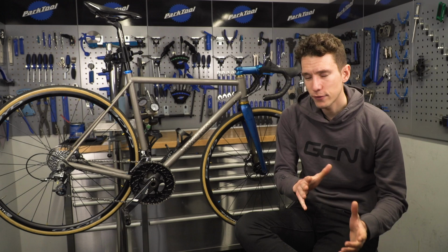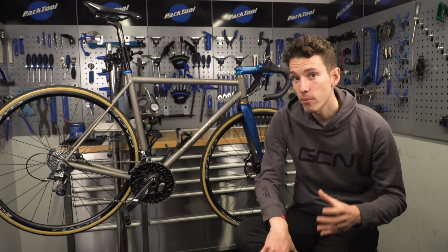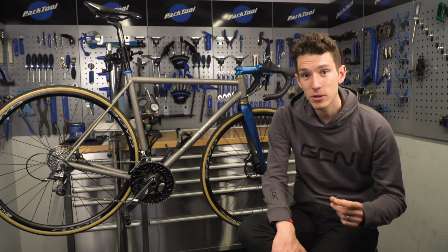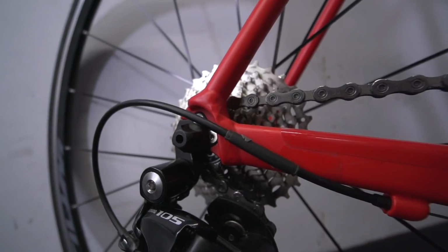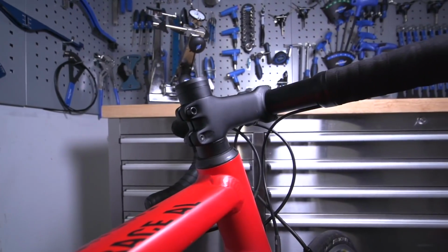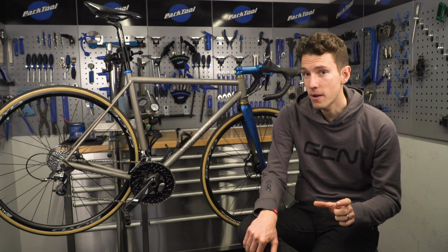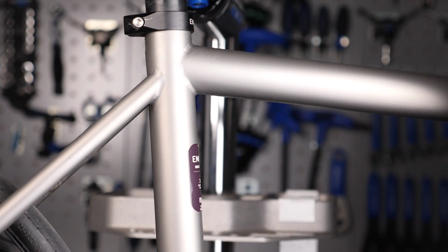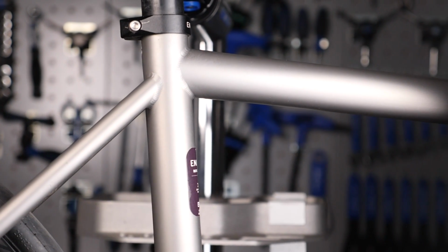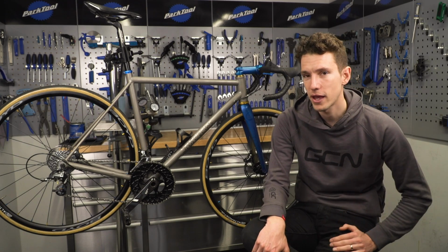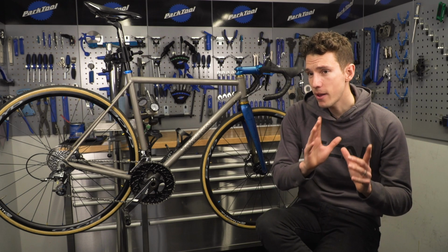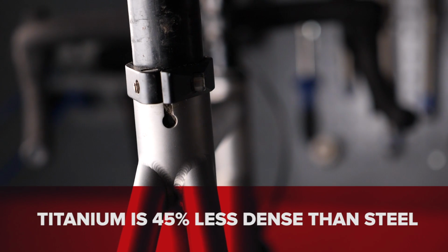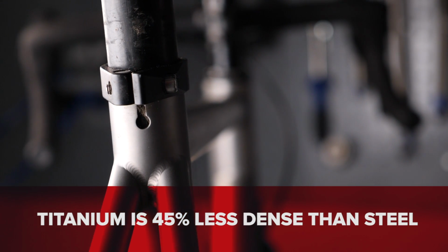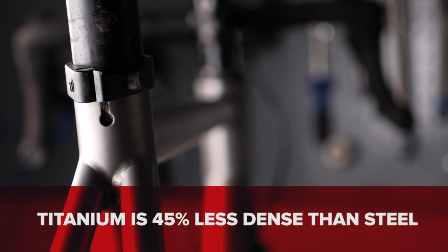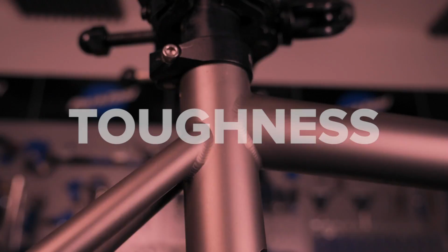And the reason that difference is actually still quite small is probably down to a measure of just how much easier it is to work and manipulate aluminium. And we'll come on to that a little bit later on. And we also have to bear in mind that super light titanium frames will also have exceedingly thin walled tubing as a result of that extra density. And then when we compare it to steel, titanium is as strong but 45% less dense. And so that explains why titanium frames are significantly lighter than steel ones.